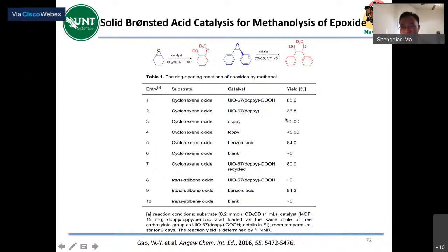the conversion yield. And of course, one of the things for this UiO, the zirconium MOF, there are a lot of defects. You can have the cluster defect, then you will have a free ligand, right, carboxylate. You can also, of course, have the ligand defects, right? One of the reviewers' questions could be whether the carboxylate is from the defects. We need to prove, okay. Then we pick a much larger substrate that cannot enter the pore. This is what we did. Using this substrate, we can still catalyze using the MOF.